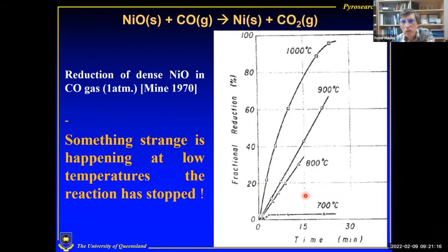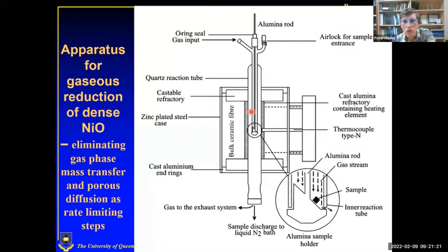Okay, so let's look at the results of what's happening in these systems. We've done these experiments by putting samples of material in this special apparatus, which allows us to put the sample into the flowing gas stream at controlled temperature, and then quench the sample out of the reaction after a given time. In this way, we were able to stop the reaction and then look at the reaction interface and see what's actually going on physically.